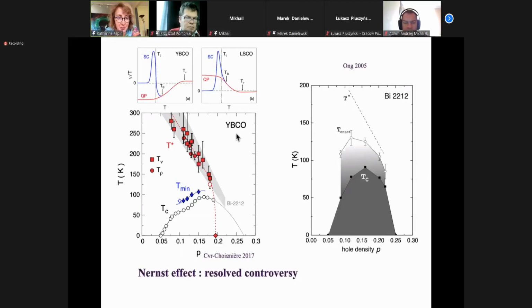But then there was another set of studies in YBCO where this temperature was assessed to be close to TC, actually not going up to T star. So this controversy was resolved, and apparently these people around Cyril Proust and Louis Taillefer were correct. Here, the mistake that was made, if I can say so, that we can get experimental mistakes, is that you have two types of carriers, as we will see, that the charge carriers are also present and they scatter through modulations, which basically in this compound by chance have the same sign as the vortex contribution to the Nernst effect. Here the sign is opposite, so those guys were able to disentangle the two effects. And now we know fluctuations are strong, phase fluctuations, but they don't go up to T star, so they cannot explain the pseudogap.